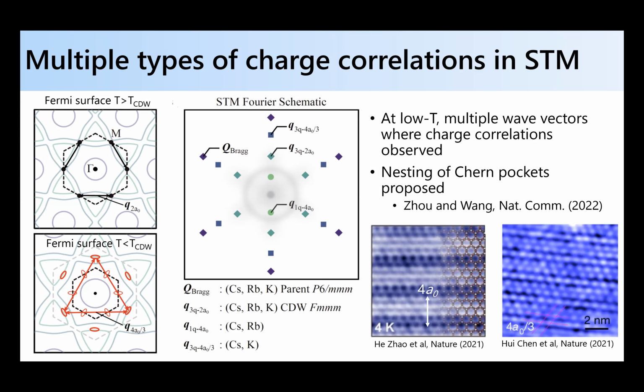So one proposal, by Ziqiang Wang's group, is that potentially this additional wave vector emerges due to a staging of electronic order. Basically, you start in the high temperature state where you have these nested Van Hove points. Then you enter the charge density wave state, and you fold the Brillouin zone, and you end up with what they call Chern pockets that are also nested. And at a lower temperature, that new nesting wave vector drives a secondary order parameter. It's still ongoing to figure out what's the origin of these, but it seems to be quite a rich spectrum at low temperature in these systems.